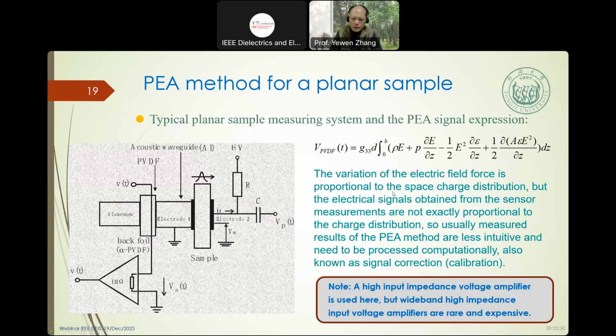The evolution of the electrical force is proportional to the space charge distribution, but the electrical signal obtained from the sensor measurement is not exactly proportional to the charge distribution. The sensor cannot get the force directly. So usually the measurement result needs to be processed computationally. It's called signal correction or signal calibration. Note the high input impedance voltage amplifier is usually used here, but a wideband one with a high impedance input voltage is not very easy to find and also very expensive.